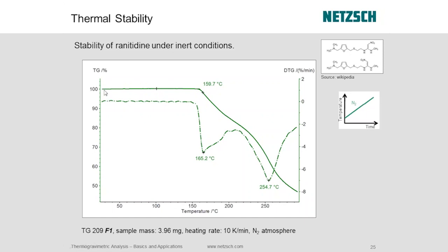It's pretty interesting. You can see as we heat it up to about 250 degrees, we're in a nitrogen atmosphere, about a 4 milligram sample. There's no mass change until we get to about 160 degrees, then we start to break from the baseline. The mass is lost. And we've got kind of a two-step process. And that's verified more cleanly when we look at that first derivative. So you can see that maximum point in the mass loss slope.